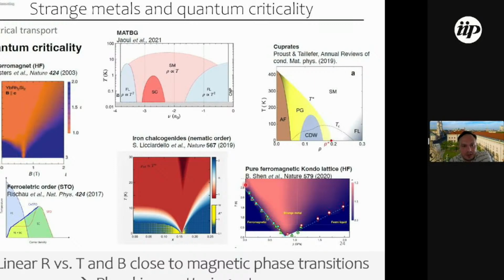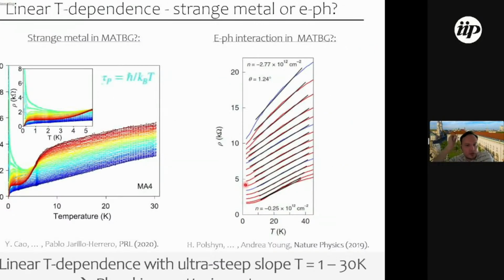Before I start with the details, I also want to mention that in principle there were already two works in twisted bilayer graphene which touched upon this topic. There was, of course, the paper by Pablo Jarillo-Herrero early on in the field, which reported some sort of linear temperature dependence and also Planckian scattering rates in graphene close to the magic angle. Basically, they just measured resistance as a function of temperature, and in an interval of 1 to 30 Kelvin, they observed these nice linear temperature dependent curves.